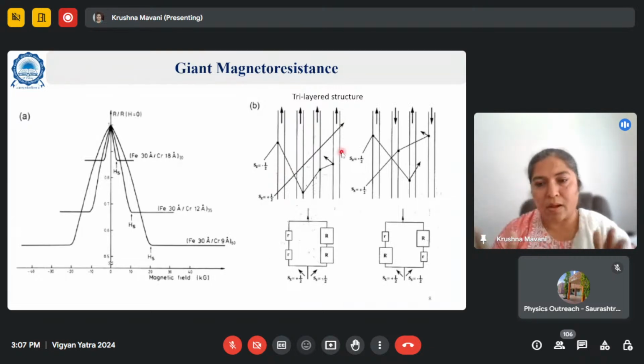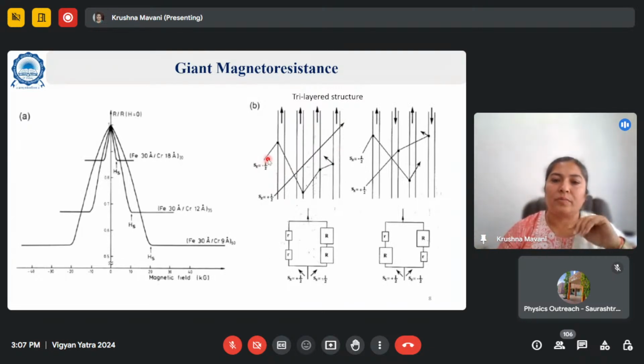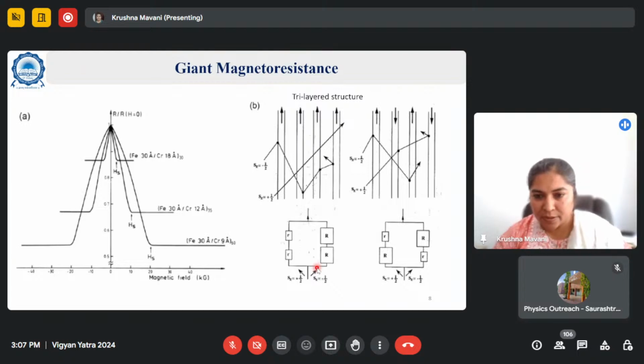Okay. So you have one electron. Suppose it is a positive half spin. It means the spin is up. It will go through easily without having any scattering at the interface. If it is spin down, because it is reverse of this orientation, it will be having multiple scatterings at the interface. Maybe it will not even pass through the multilayer. Okay, this is the situation. It can be conceptualized in a kind of two channel resistance circuit, if you can understand this very easily.